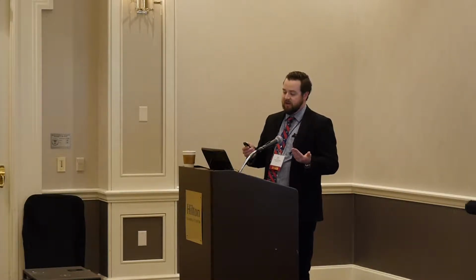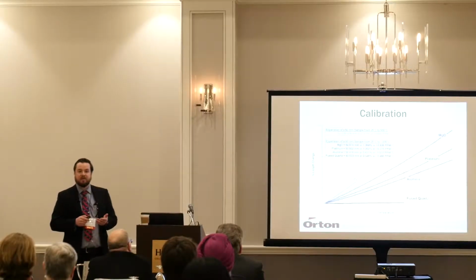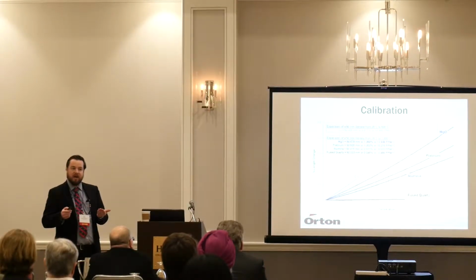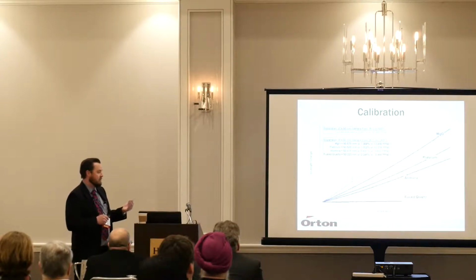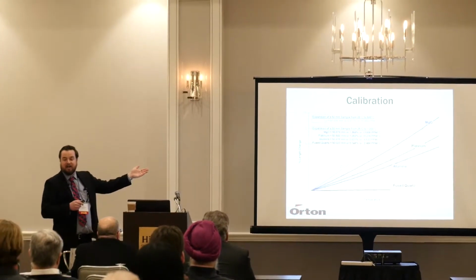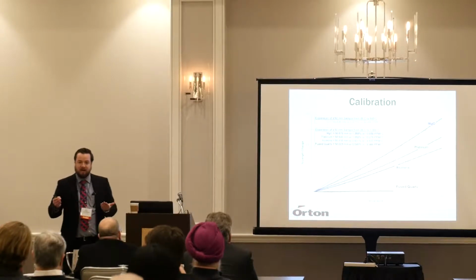So at the end of the day, what does all of this look like? Well, it's a very simple curve. Temperature on the bottom, percent change on the y-axis there. So these are different calibration materials. As I said earlier, it's very important when you calibrate it to have the same length of sample. You also want to have a calibration that's in the same regime. So if you're going to be testing a material, something like copper or a metal, platinum and copper, you're going to want to calibrate against the standard that's going to experience those same percent changes, because like making a measurement, you want to make sure that you're making it on the same length scale.